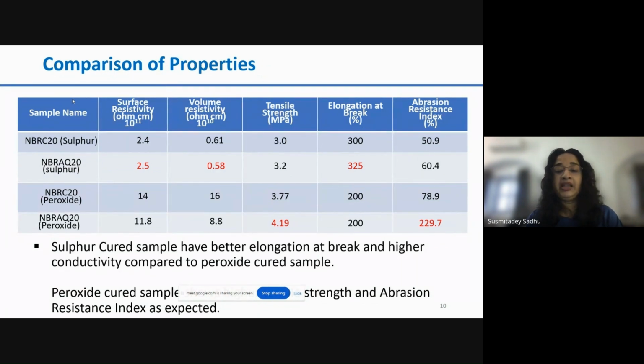But on the other hand, the mechanical properties like tensile strength and abrasion resistance are better for the aqua regia filled sample at 20 phr level with peroxide curing, which is quite expected because in peroxide curing the nature of bonds is only C-C linkages, so that is expected to give higher strength. The elongation at break again is better in case of sulfur curing, which is again as per our expectation. So from here, we decided the overall properties are better for sulfur curing.